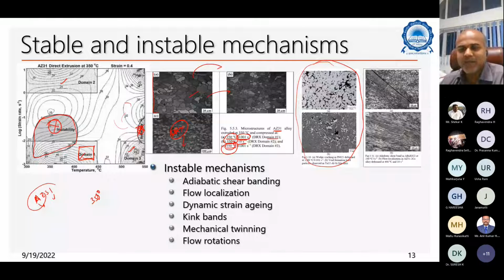Most of us who work in this failure analysis part, many people approach us saying, okay, I actually got the sample failed. Why has this failed? The first thing we look at is the microstructure, the initial microstructure. When we see a very uniform microstructure, we say that it could be a design problem, or an overload problem or something. But the moment we see any of these undesirable microstructural features in the sample, we say that while processing this material, something would have happened. Something which we don't know, but this is the reason.